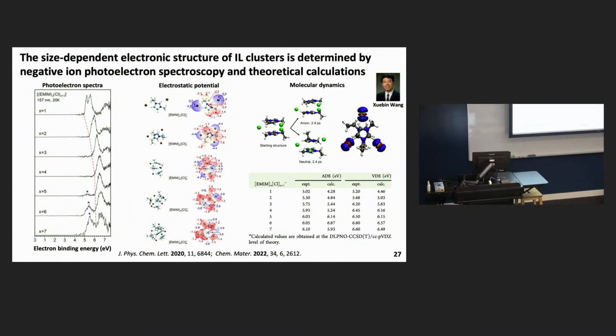The electronic structure of these is also very important because we're planning to immobilize them on electrodes and use them to try and remove solvation shells from ions. So we obtain photoelectron spectra of these clusters as shown on the left-hand side here in collaboration with Xuebin Wang. This gives us an idea basically of the energy required to remove an electron as a function of the size of the clusters. We were also able to calculate the electrostatic potential for each of these clusters, which gives you an idea basically of how the charge is separated on these surfaces and where a cation might selectively interact with these clusters on an electrode. On the right-hand side are some of the results showing the change in charge when you remove an anion, and then the agreement between what was calculated and what was measured experimentally, which is, in this case, reasonably good.